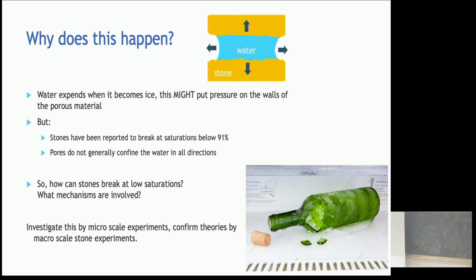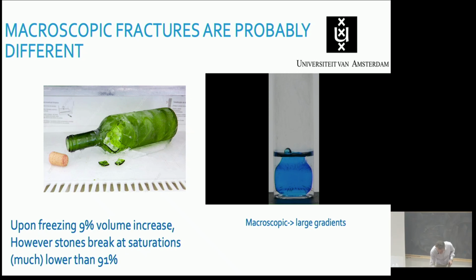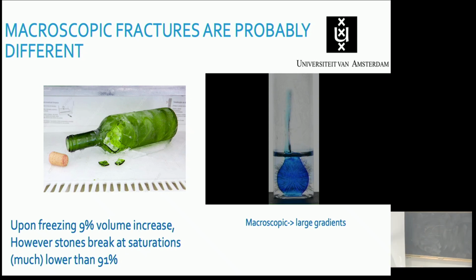Yeah, and so the simple question we asked is what happens really at the micro scale. Menno has shown you what happens at the macro scale, but because it's very pretty, I will show it to you again. So this is a vial in a freezer, and because there's large gradients, because it's a centimeter size sample, it freezes first close to the walls, and then you have a liquid pocket, and when that liquid pocket freezes, it expands, and then the vial breaks. But this is not at all probably what happens in a porous medium.